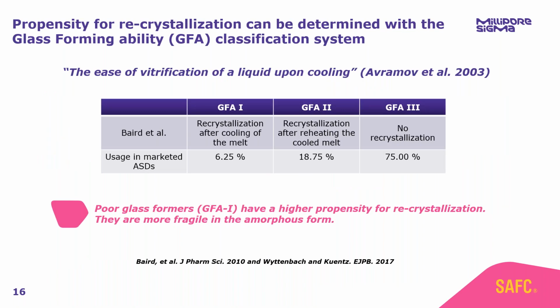And one of the ways in which we can do this is by determining the glass forming ability of our molecule. The glass forming ability is essentially the propensity of a molecule to recrystallize. Avramov in 2003 described it as the ease of vitrification of a liquid upon cooling. Essentially, if you have a liquid and then you solidify that liquid back to a solid, how likely is it that that liquid will recrystallize? Based on this theory, Baird et al. developed a framework to experimentally determine the glass forming ability of a molecule.